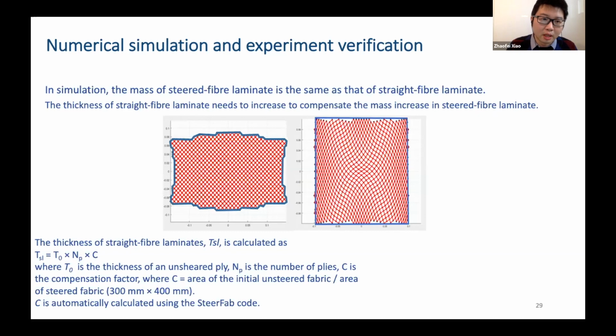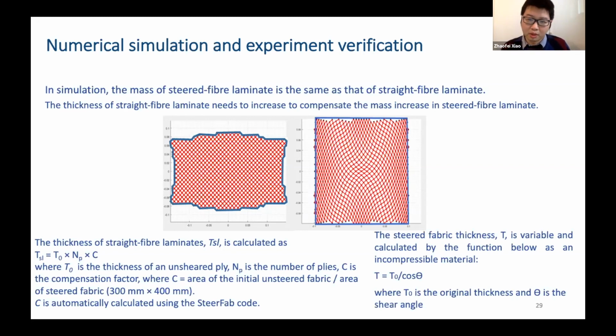So in the simulation, we increase the thickness of the straight fiber laminate to compensate for that mass increase in the steered fiber laminate. So the thickness of the straight fiber laminate equals the original thickness times the number of plies times the compensation factor. The compensation factor is just the area ratio from the initial stage to the final steered pattern. We also assume the fabric is an incompressible material, hence the thickness of the steered fiber equals the original thickness divided by the cosine of theta. Theta is the shear angle of the fabric.